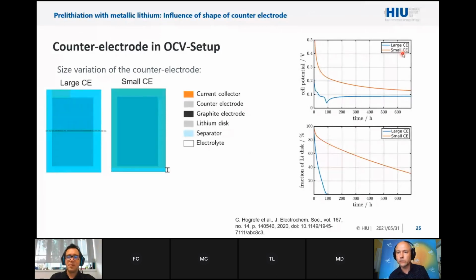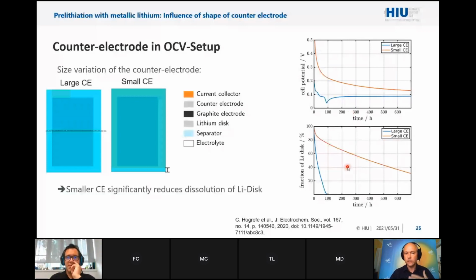For the small counter-electrode, there was a very smooth dissolution, this very smooth degradation of the cell potential. There is no stepwise intercalation and reintercalation and relaxation. And also the fraction of lithium disk was dissolving much, much slower for small counter-electrodes. And this means that the smaller counter-electrode had a significant influence on the dissolution rate of the lithium disk.